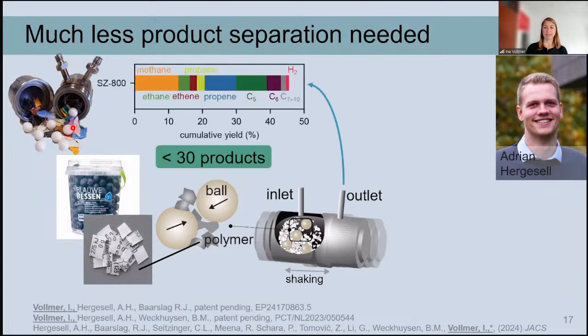And what we get out is then actually in the gas phase. And to obtain this gas phase, we need an inlet and an outlet to this vessel. So we send a stream of nitrogen through this vessel, and that elutes our products. And when I first tried this out, I was really excited because I had worked on thermal pyrolysis before, and I'd seen that if you get to 250 degrees or something, you slowly start to see some gas phase products. But with this, without any additional heating at room temperature, we could see gas phase products coming out of this ball mill. And this was really exciting and also a bit unexpected.